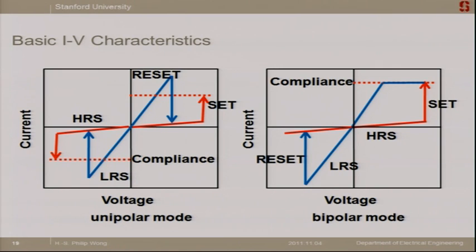There are two modes of operation of these RRAM. One is what I call the unipolar mode. The other one is the bipolar mode. The bipolar mode is easier to understand. So here's current versus voltage. Let's say you start from a high resistance state, HRS. You ramp up the voltage, and at some point it will go through a soft breakdown of the metal oxide. So the current will shoot up and become the low resistance state.